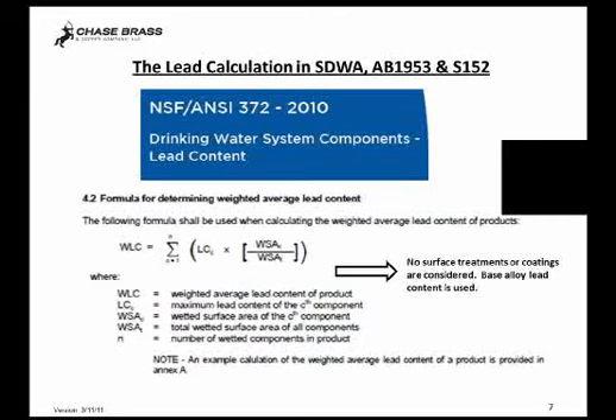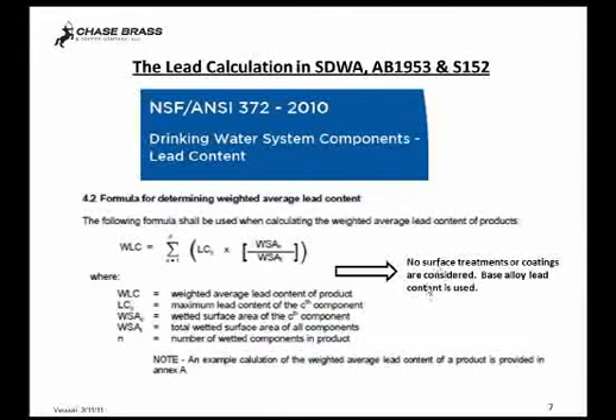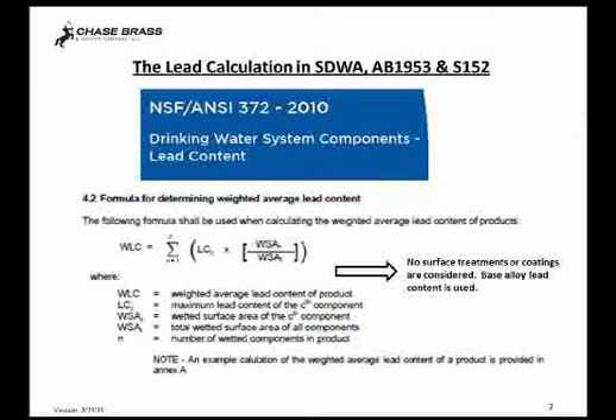The particular requirement of this standard, though, also indicates that no matter what you do to the surface to reduce the amount of lead that's in touch with the water, or if you put a coating on there, that's disqualified from the calculation. They use the bulk material's lead content for the calculation, and these other types of treatments are not considered part of what has to be done.